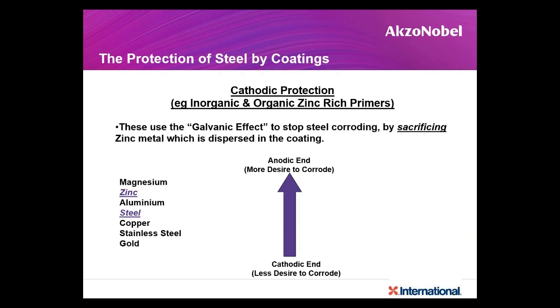Then you have stainless steel, which is more corrosive. Copper is more corrosive than stainless steel. Then you have carbon steel, which is much more corrosive and is used in large quantity. Then you have aluminium, zinc and magnesium. So as you go up this chain, the rate of corrosion increases. So when you look at steel in the center, if steel is protected by a material which is more reactive, for example zinc, then steel can perform for a longer time.